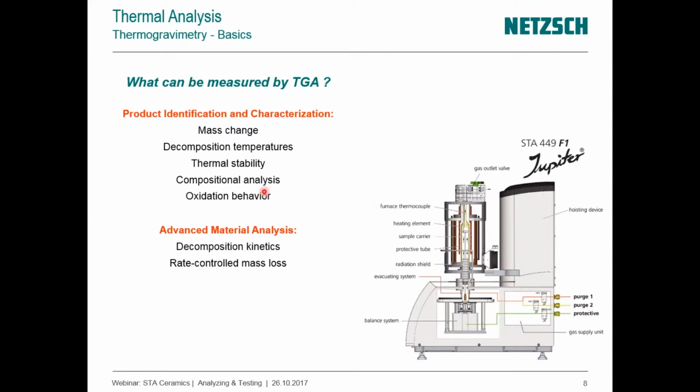So an instrument itself could measure a broad range from the temperature point. And there are also special furnaces, for instance, for this water application, where you can really go in with, for instance, pure steam. So we have a special assistance heater to prevent condensation. And these techniques can, for instance, with steam be applied up to 1200 degrees C. So this is quite special, the temperature range.